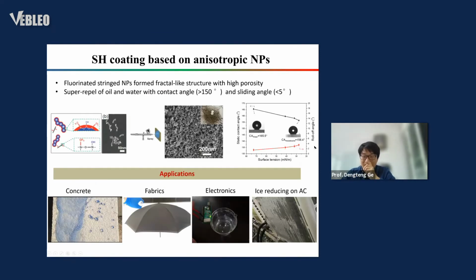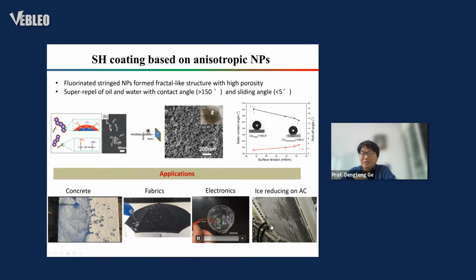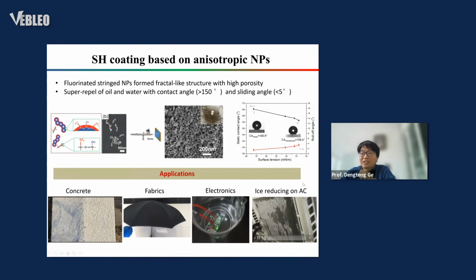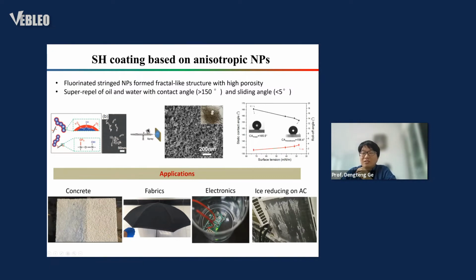And also, besides the spherical nanoparticle, we also use the stringed nanoparticle. With this special nanoparticle, we can make a fractal-like structure with very high porosity, and they can generate very high contact angle and very low sliding angle for oil and water. So for hexadecane, they also can make more than 150-degree oil contact angle. If we coat it on different substrates like concrete, fabric, even electronics, they also can work underwater. Even if we just coat on the fin of the air conditioner, it can reduce ice faster.